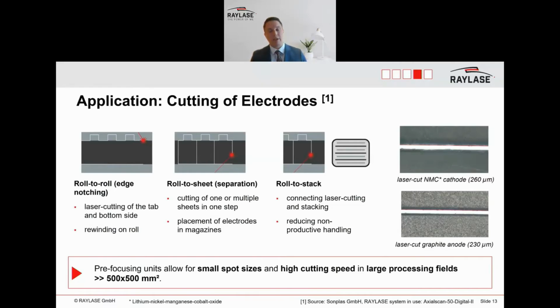They developed a specific laser process that ensures very good cutting edge quality with very, very low heat affected zone, as you can see on the right here, with the images of the laser cut NMC cathodes and the laser cut graphite anodes. And again, here we are operating in a very large field and still achieve a very small spot size and a very high cutting speed. And this combination is only possible if you go into the pre-focusing direction, because in a normal 2D scanning, you wouldn't be able to achieve these large fields.